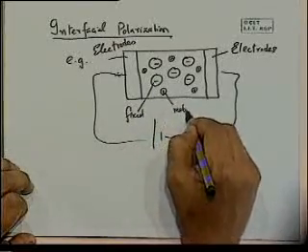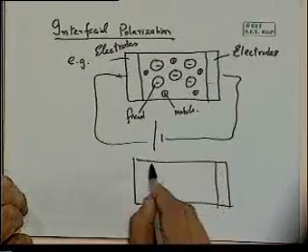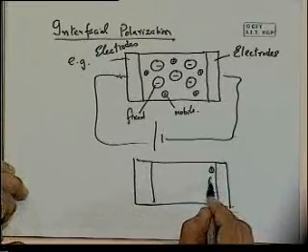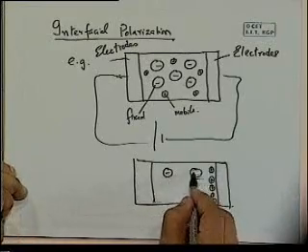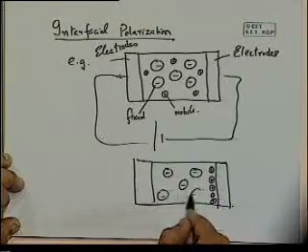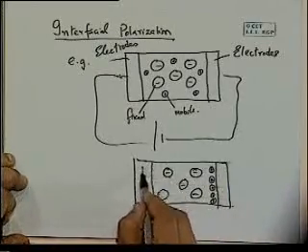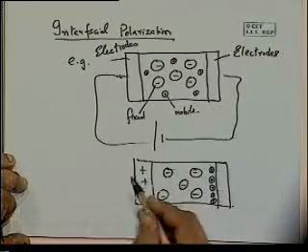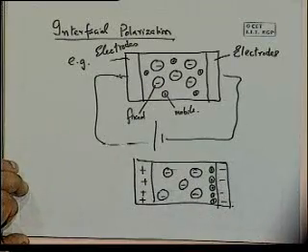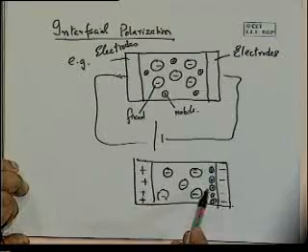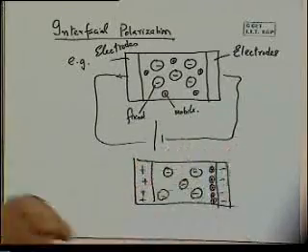Okay. And then what will happen is, in the next view, the positive charges have more or less accumulated out here. And the negative charges may have shifted a little bit, but are more or less in their original positions. Now, we have applied a voltage here, so we've got charges, what we called the free charges yesterday, in the two electrodes here. As this charge keeps on building up here, to compensate for that, we will get more electrons flowing into this electrode. So there's going to be charge buildup there.